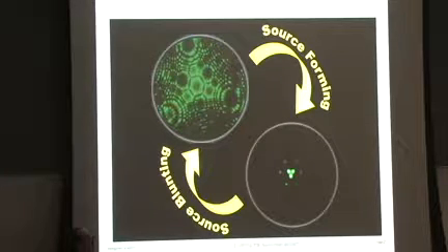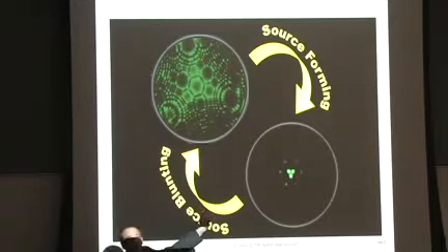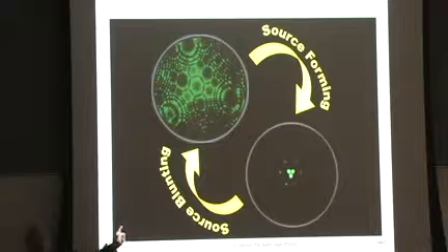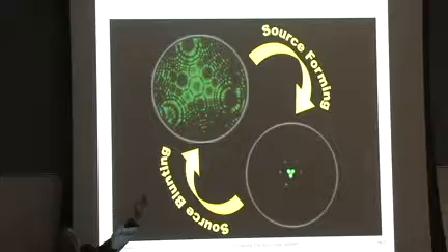And the way to go back is actually quite interesting. You just turn up your voltage a little bit more, and those atoms I mentioned will pop off at around 4 or 5 volts per angstrom. And they don't make popping sounds, but you can almost imagine them disappearing one by one until you get this rounded end form, where now the field is shared by hundreds of atoms.